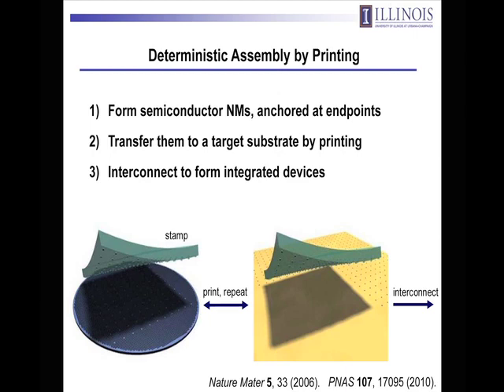In order to make this work, it really requires careful attention to be paid to the physics of soft adhesion between this elastomeric stamp and the undercut etched silicon nanomembranes. In particular, what you need is the adhesion to be strong enough between those nanomembranes and the stamp so that when you peel the stamp back, you can fracture the anchors so you can efficiently ink up the stamp with that material. But you don't want it to be too strong because you need to get the nanomembranes off of the stamp and down onto the target surface, also at high yields. And so what you really need is a mechanism for switching the strength of adhesion between those nanomembranes and the stamp from a strong state for the inking part of the process to a weak state for the printing part of the process. And we've spent a number of years working on that problem.